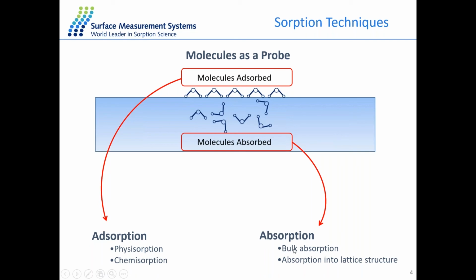And in case of the absorption, it could be either by bulk sorption or the absorption into the lattice structure. The bulk sorption is more related to the vapor-induced phase change happening in the bulk of the material. So we can determine the glass transition temperature and humidity for the sample. Or we can also determine, as in the previous presentation, the permeability or the diffusion of water vapor through a thin film sample or through a particle or powder sample. And the last kind of interaction is more related to hydrate formation or solvate formation in case of organic vapors. So we can study the kinetics of this hydrate formation process or the structure of this hydrate.